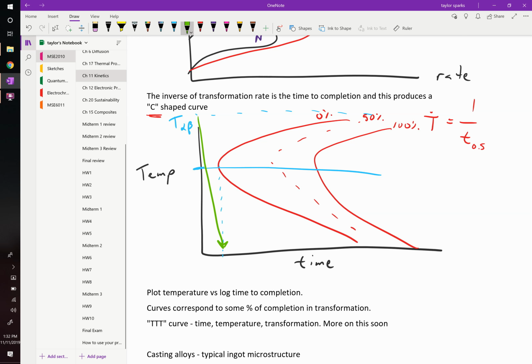Instead, you form a metastable phase. If this was liquid and solid again, that liquid you wanted to turn into a solid, but if you quench it fast enough, you reach a region where you now have metastable liquid. It should not be stable at these temperatures, but it is for a really long time. This is on a log scale where you plot this, so that might be years or centuries. For the case of the diamond on your diamond ring, you've quenched it so quickly that now you have diamond, which should not exist. It's metastable. And if you give it long enough, it will start to turn into graphite.